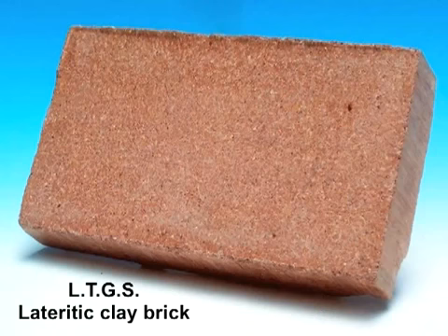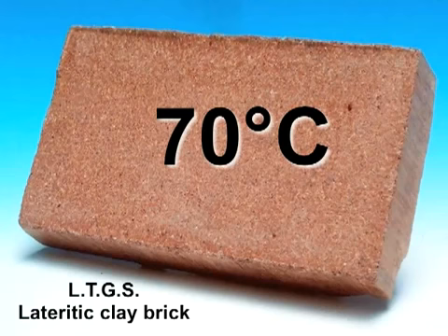Here, this is a brick made out of lateritic clay, but instead of firing it at 800 or 900 or 1000 degrees C, which requires a lot of wood, which requires a lot of fuel and even gas or oil, we'll do it at 70 degrees centigrade.